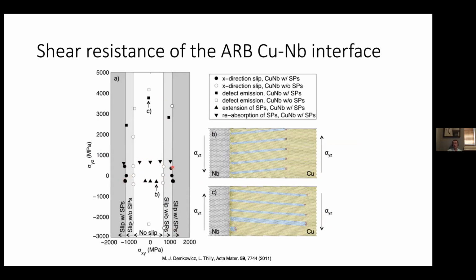Instead of slipping, what happens is that this interface actually begins to emit dislocations into the neighboring crystals. So in other words, if you were to start applying shear stresses to this interface along the direction perpendicular to this Burgers vector that I showed you here, you will actually see partials getting emitted from the interface and then gliding into the neighboring crystals. So rather than slipping, this interface prefers to make the neighboring materials yield, so the neighboring crystal and grains yield. And so the structure of this interface has a very direct and profound influence on the mechanical properties, in particular the shear resistance.